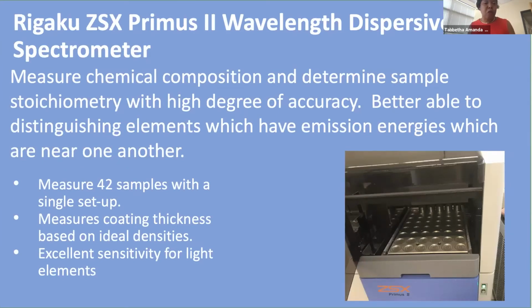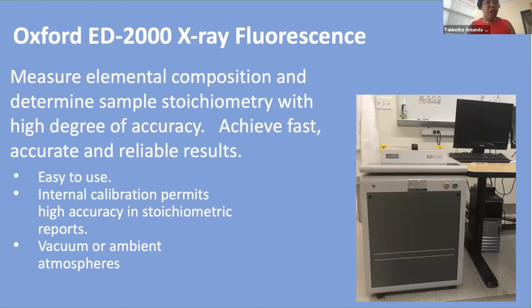Also under spectroscopy, moving away from microspectroscopy and just into sample spectroscopy, so we're not able to specify regions of interest, we have a wavelength dispersive spectrometer that's able to assess 42 samples in a single setup, and your samples are either solids or powders that are placed into the sample holder. And we also have a newer instrument than the wavelength dispersive spectrometer. We have the Oxford ED2000 X-ray fluorescence instrument. And again, this instrument is able to give you elemental compositions with a fairly reliable result.